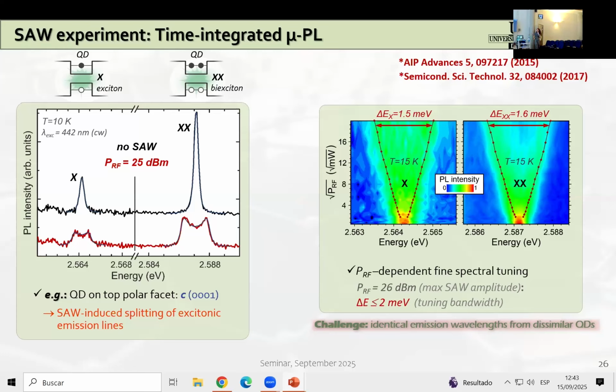So these results actually show that the acoustic wave can be used to tune spectrally the quantum dot emission. And this is an important result because, as I mentioned before, with this, we are basically able to address the challenge of having indistinguishable photons. By applying the acoustic wave, we can affect the dissimilar quantum dots and force them to have identical emission wavelength as long as their emission energy is within the approachable bandwidth here.